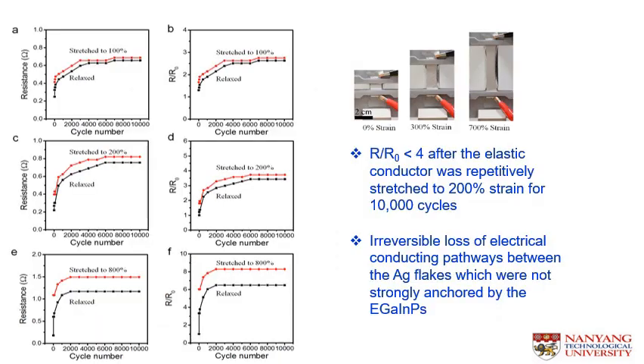This synthesized stretchable conductor shows a good performance as a function of cycling number, giving a resistance increment of less than 4 times, as shown in figure D, when it's repetitively stretched up to 200% strain. At higher strain state, in figure F, there is a gap between the stretch state and the relaxed state. Nevertheless, the resistance is still relatively stable.